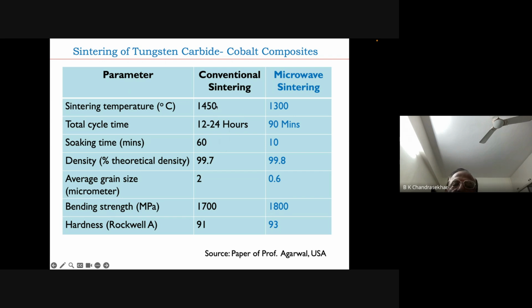Therefore the sintering takes place at a relatively low temperature of 1450 degrees centigrade. For tungsten carbide, I would say that is a relatively low temperature, and the total cycle time, depending upon the size of the component, can be anywhere from 12 to 24 hours, let's say one day. So you start the furnace today morning, and the next day morning, you come out and you will be able to open the furnace.